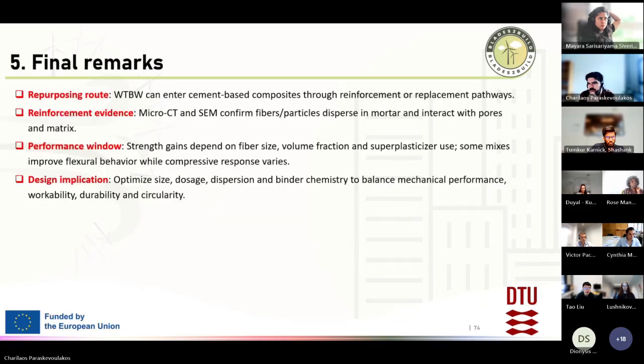Next, please. So the final take-home message is that the turbine blade waste can enter cement-based materials through the reinforcement and replacement pathways as we presented. The reinforcement evidence is proved by the micro-CT and the SEMs. We know that when these fibers distribute in the mortars and interact with the pores and matrix, they can help with the mortar flexural strength specifically. In the compressive strength cases, when we do the compressive testing, the fiber can also bridge the cracks. So in some cases of small fibers, they can also help with the compressive strength.